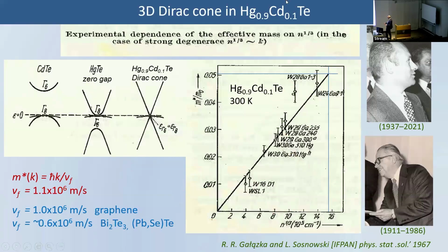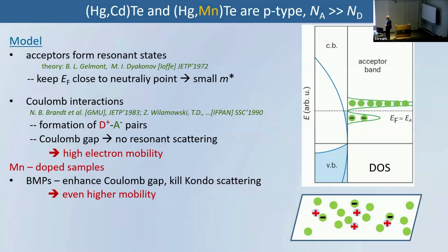So now we have the possibility of a topological material in the range of concentration below this crossing point. What is interesting is the crossing point and the topological range. Let's start from the crossing point. What was found, an interesting finding, is that these materials are p-type, which means that there are acceptors in the sample which can bind holes. And since the gap is 0, as you see here, these acceptor states attached to this heavy hole valence band must be degenerate with the conduction band. And this degeneracy has several important consequences.